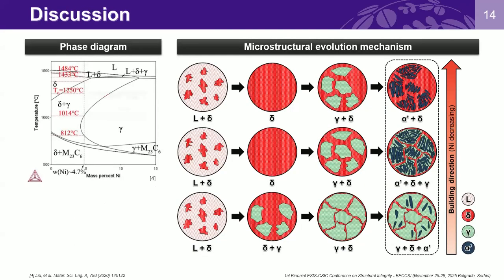To analyze the phase transformation, the phase diagram is also indispensable. The estimated parameters such as melting temperature, A1 temperature, and A3 temperature are provided by the equilibrium phase diagram. Combined with the result of the thermal history, the microstructural evolution mechanism was systematically reviewed, as shown in the schematic diagram.